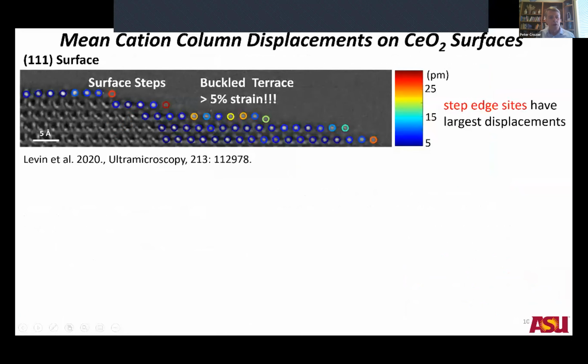So Ethan Lawrence and Barnaby Levin went and decided to analyze the mean cation displacements from these movies, and the error, the uncertainty in the measurement here is about 5 picometers. And so what they've done is they've measured as a function of time the displacement of these cation columns as a function of position along the surface here. And what you see is that the step edges are indeed much more mobile. The mean displacements are on the order of 25 picometers.